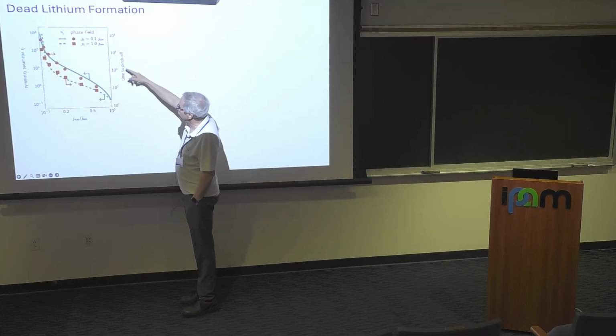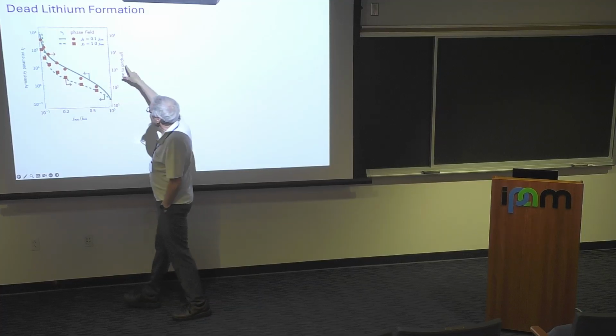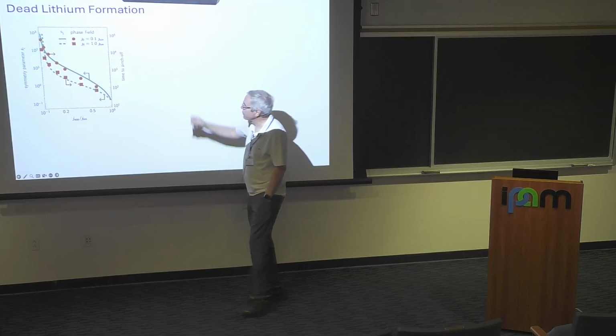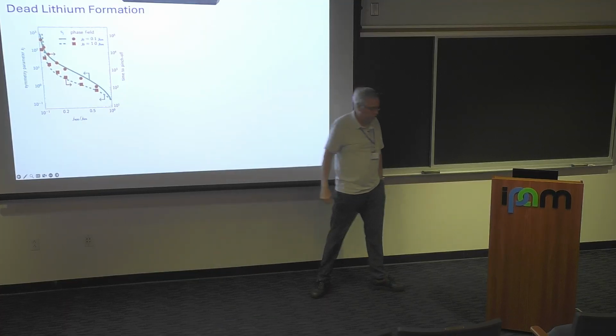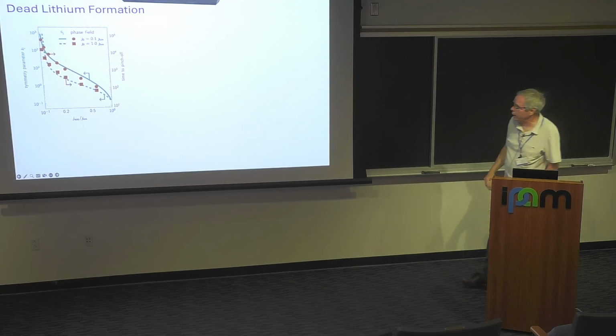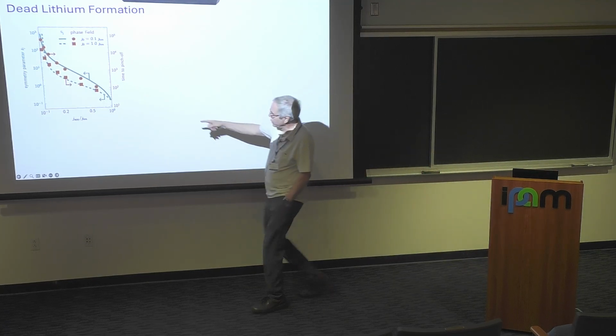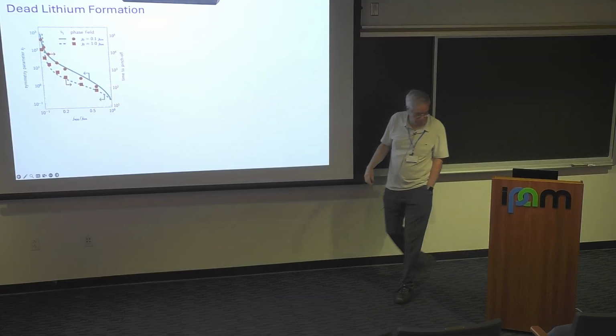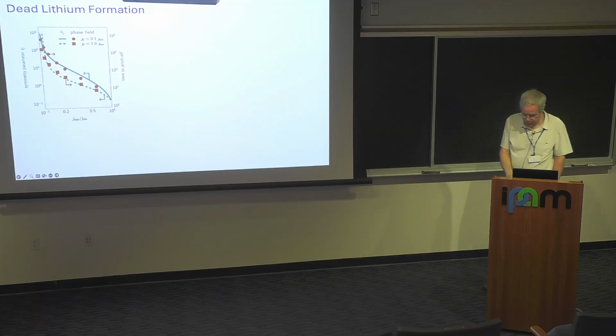And the time to pinch off and the symmetry parameters that you get agree quite well with the phase field method for various exchange currents. You see up there. The model does not work, I would say, when the applied current is very close to the limiting current, because that's really a pathological case where you have almost no solute concentration at the interface.